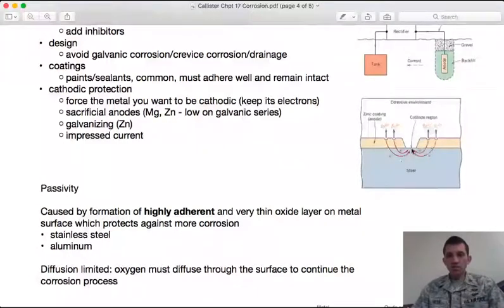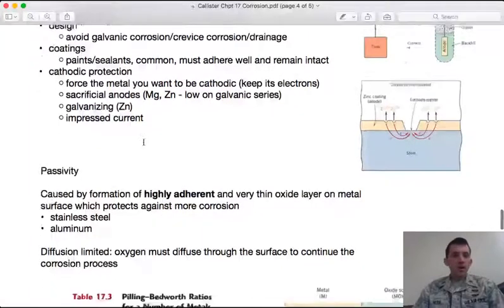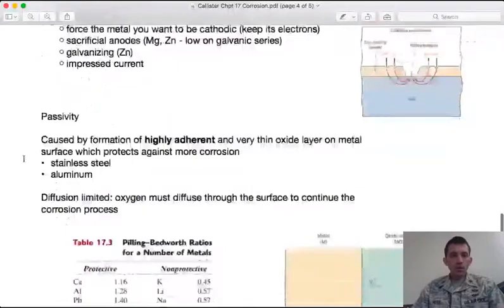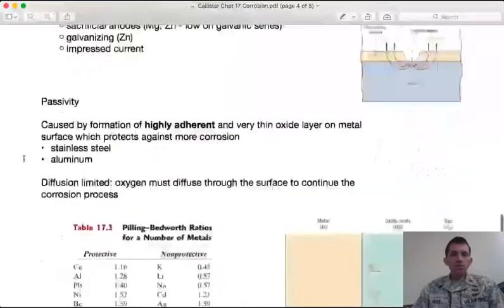And this especially works if you have damage to that surface. You're going to have uniform corrosion on the galvanized steel. So if you ever see that white chalky surface residue that can form, that's uniform corrosion of the zinc. Also, if you were to have a scratch, that region becomes the cathode and has electrons donated from the surrounding zinc. So it's self-protective. Okay, so that's something you can do from the outside.